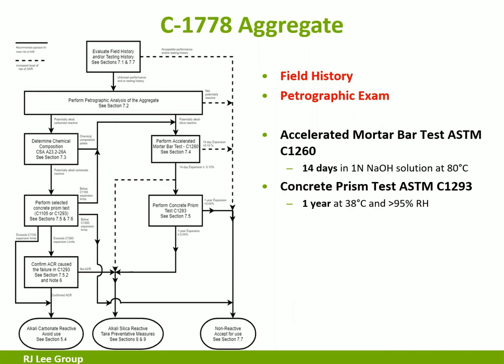But what you can do, if you collect the data and do the investment up front to evaluate your aggregate, you can then use the accelerated test method to monitor your aggregate. Because if you have the data to say that your accelerated test method correlates well with the concrete prism test, then you will be able to use that quicker method to monitor what you have and see if there's any changes. So part of this guide, it goes on to really tell you how you can mitigate your aggregate for use in concrete. I'm not going to talk about that today, but that is really part of the program.